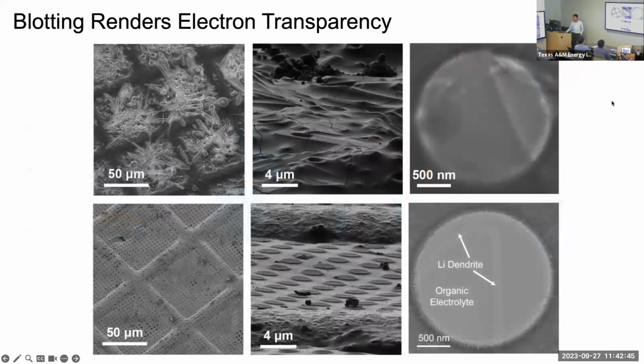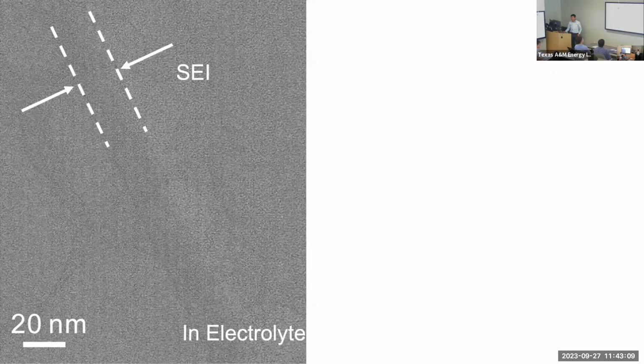So now we have this lithium dendrite, bottom right, frozen inside organic electrolyte without crystallizing the organic electrolyte, maintained as an amorphous phase. If your organic electrolyte is too thick, it's like top left, right? There is very much mass, too thick. With the electron beam, you cannot see anything. So let me share with you, we have made the discovery right here. This is in the electrolyte state.